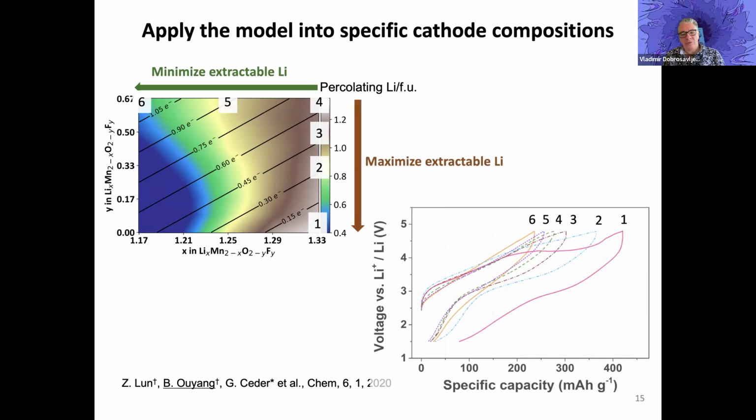But are these pairwise forces that you get? You didn't say. Not really. Typically, that's the idea of a cluster expansion, because the Ising model is like first nearest neighbor pairwise. But we can generalize it to any order. We call this many body, but real many body physics people will not agree with it. We have 3 atom interaction, 4 atom interaction, 5 atom. Of course there are multiple atom interactions when you have electrons moving around, right?